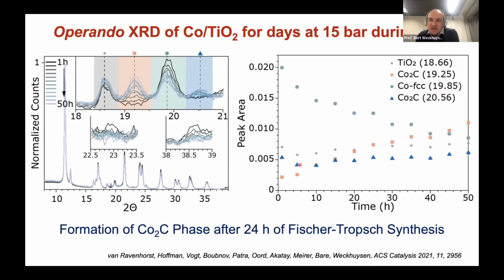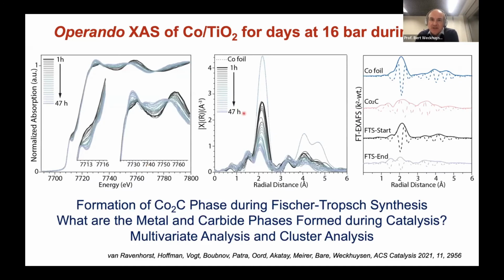You can also see that you have another peak, which is somehow increasing, but not that much. But in the beginning, you don't see a lot. And that the cobalt metal phase is actually dropping. What we first did, we reduced it, and then we did catalysis. And here the same. We actually reduced it, and then we did catalysis. This is the X-ray absorption spectroscopy at 16 bar during Fischer-Tropsch. I will discuss the spectra more in detail, but I hope you see that a lot of changes are happening.